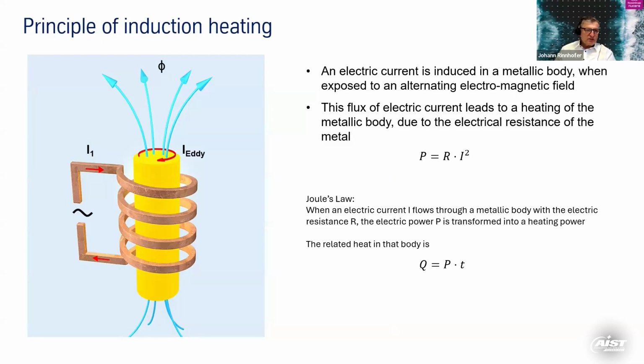When you have an alternating current in a water-cooled copper coil, which is shown here, you put in a metallic body. The changing current in the coil also induces a current in the piece, in the steel body, and that generates heat in the end. The power is the resistance of the material times the induced current squared, and the heat is the power times the heating time.